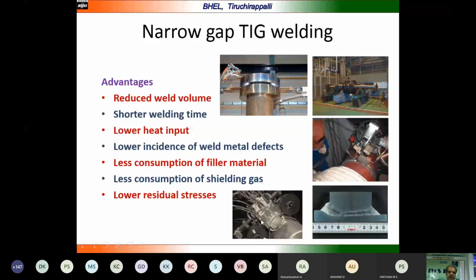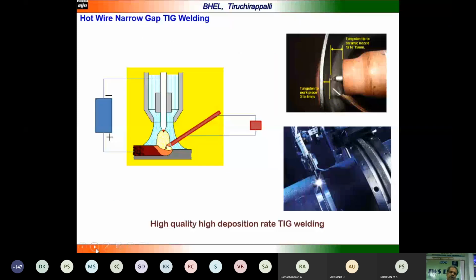So far, we saw only the conventional TIG welding process, where cold filler wire is added. Here, a small transformer type power source is added and connected to the filler wire, and the filler wire is heated almost to melting temperature. When it enters the weld pool, it melts very quickly, so the penetration and the deposition rate can be increased, and it can be as close as possible to the MIG welding process or GMAW process, and that is a major advantage. This is used nowadays because of the advantages of high productivity as well as clean weld.